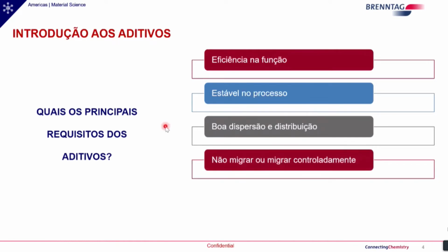So the additives should not migrate. If it migrates, it has to be controlled. So when we talk about a UV stabilizer, migration must happen because it really acts on the surface. So we have to displace it to the surface. Totally different from a flame retardant additive.